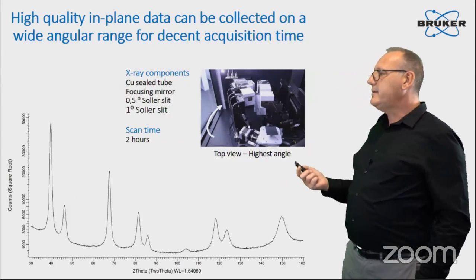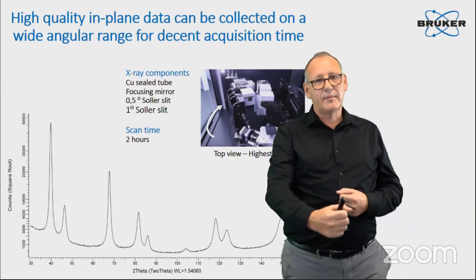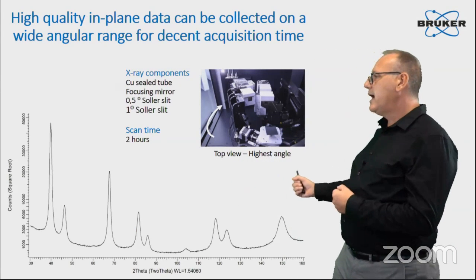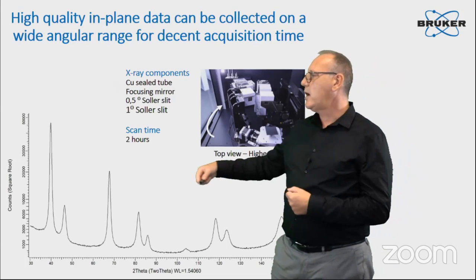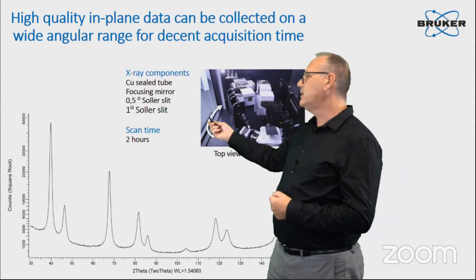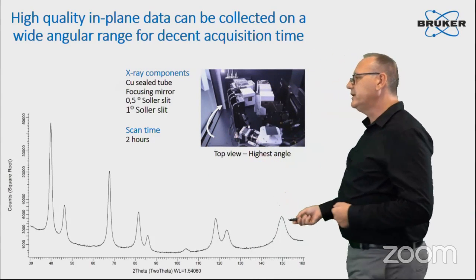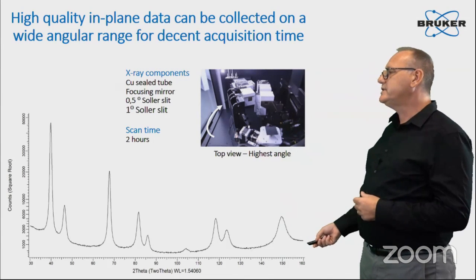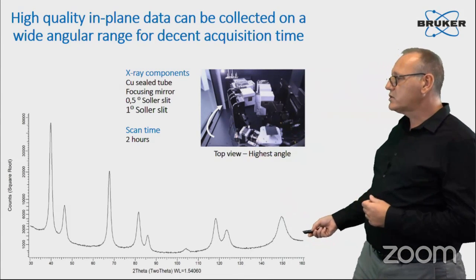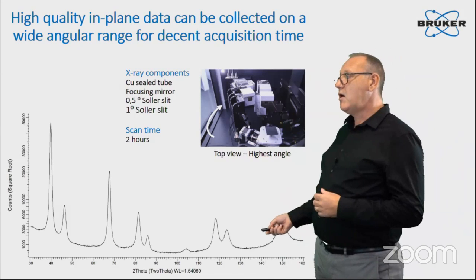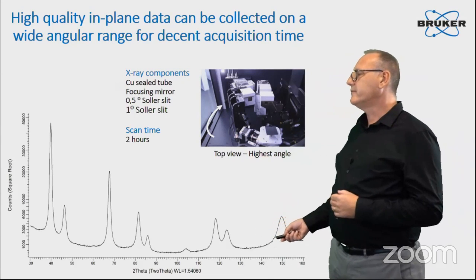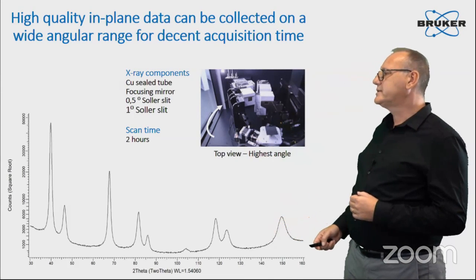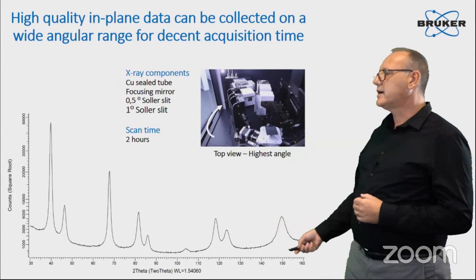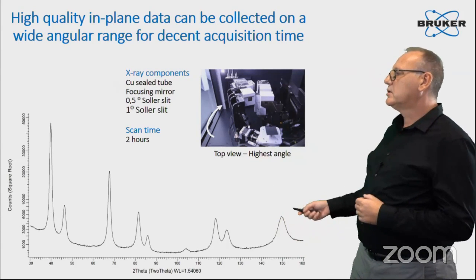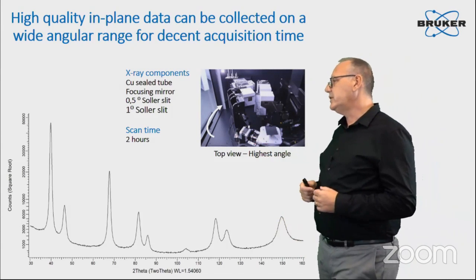If we do the same with the non-coplanar arm, so the in-plane scan, and also go all the way up to the highest accessible angle, which was also in this case 160 degrees in plane, we also have in 2 hours a very decent diffractogram. So we have all the peaks, and even including the last peak here. And this is close to the collision limit, actually.